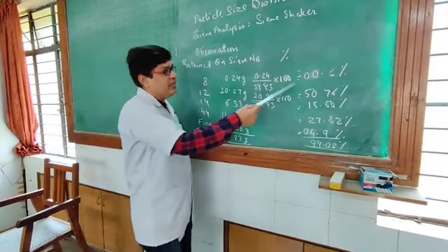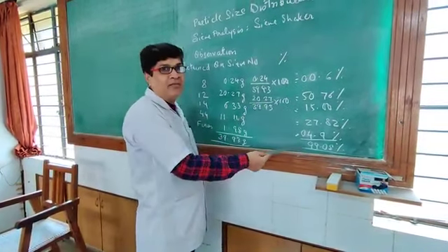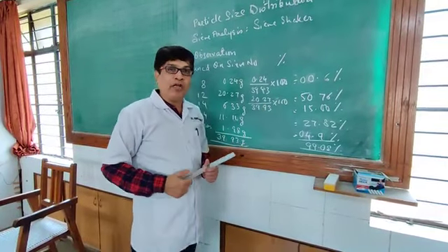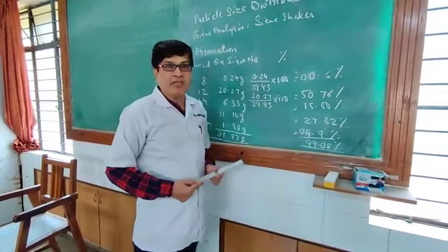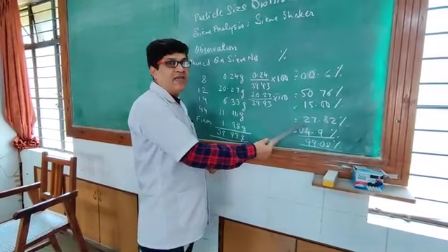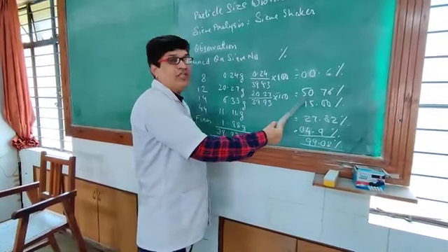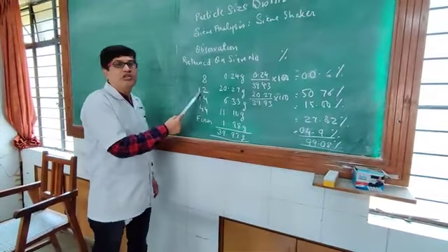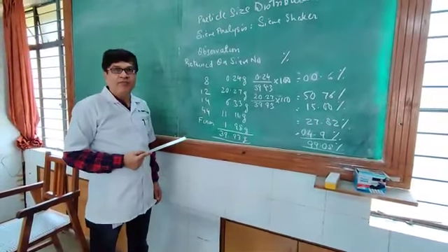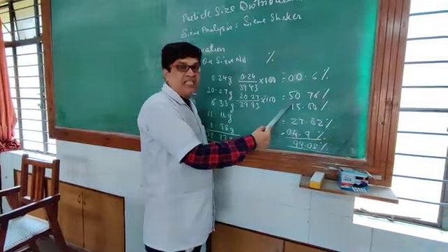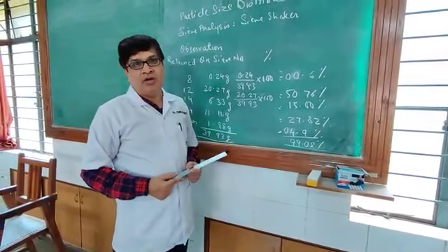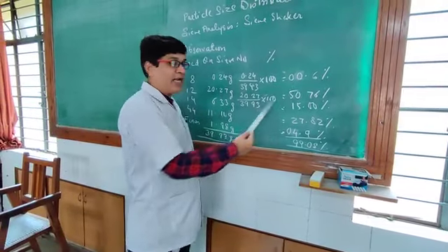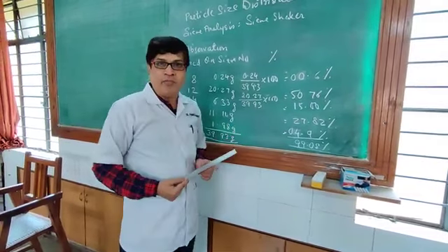In this way, we see the distribution of granules. The coarse granules are 0.6%, whereas the fines are 4.9%. The granules in between are 50, 15 and 27. You can see nearly 50% of the granules are retained on sieve number 12. The more this percentage increases, the more uniform your granules are in shape. Here the granules are more or less uniform, but not very uniform.